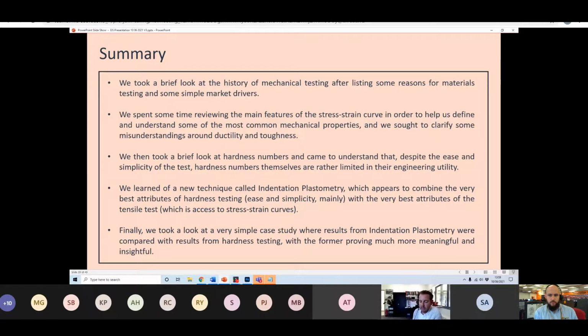Let's suppose that the case hardened layer hypothetically is 200 microns thick and we indent to 100 microns. Then really what we're probing there is the case hardened layer. And therefore what we infer is the case hardened stress strain curve. So it's all about scale, and it's all about people understanding what it is they're testing, what the machine is doing, and using the system and approaching their testing in an intelligent way. It's: what are you trying to achieve with the test? And the problems that you're identifying here, or the questions you're asking, are relevant not just to indentation plastometry, but to hardness testing as well. Anything that's like local surface-based property measurement, you need to think about these things. So it's not unique to indentation plastometry.